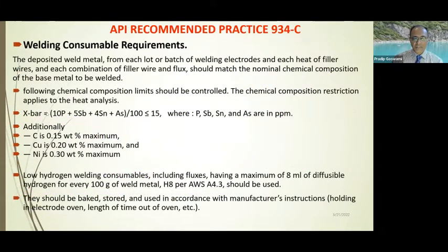And welding consumable requirement, basically the X-bar should be less than 15. X-bar is a summation of phosphorus, antimony, tin and arsenic, all these tramp elements, divided by 100, and this particular number should be below 15. And additionally, carbon should be restricted to 0.15% maximum. Copper is 0.2 maximum, and nickel should be 0.3 weight% maximum. And generally, the restriction of copper is to control the hot cracking tendency at elevated temperature. These equipments are exposed to a temperature of 400 degrees C plus, right? Restrictions of those are very important.